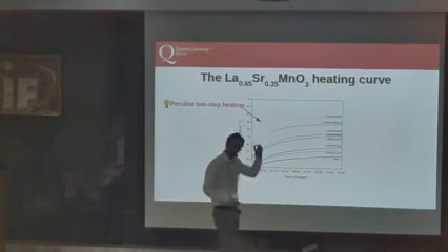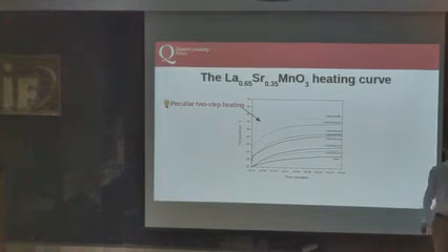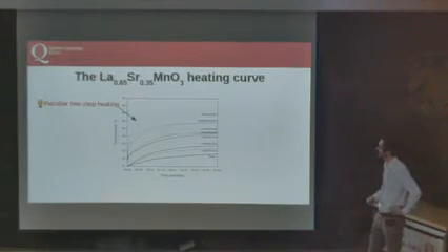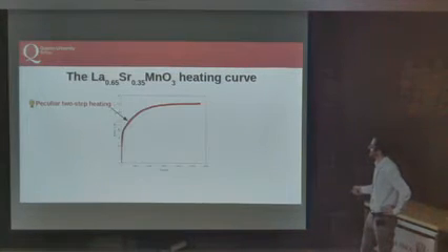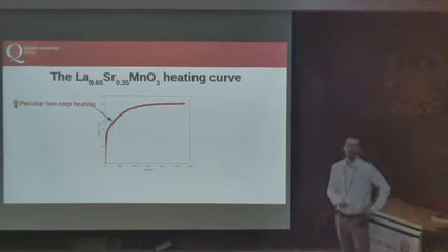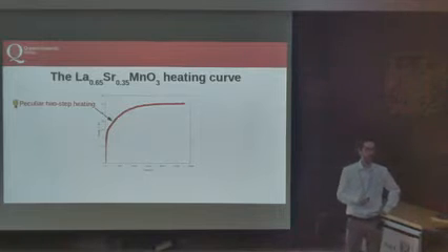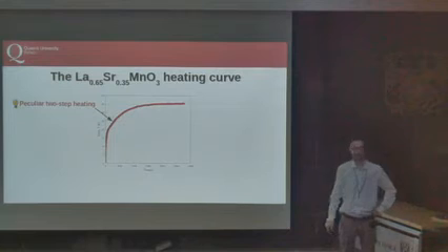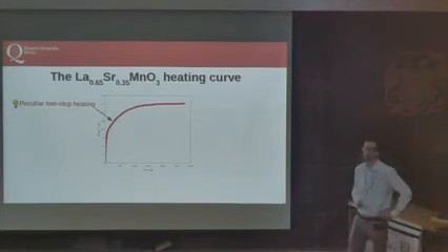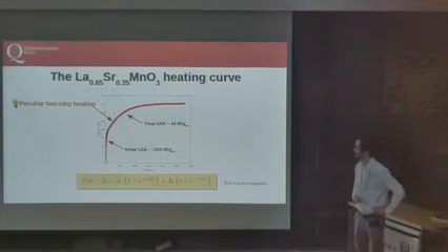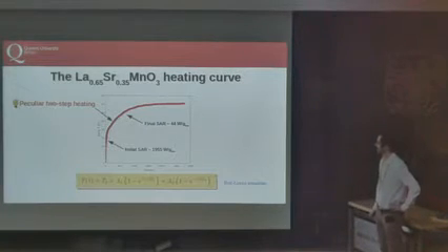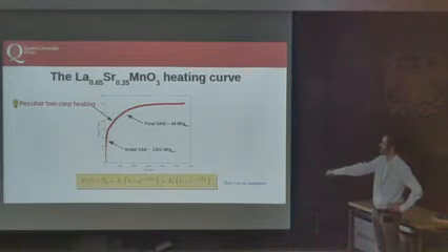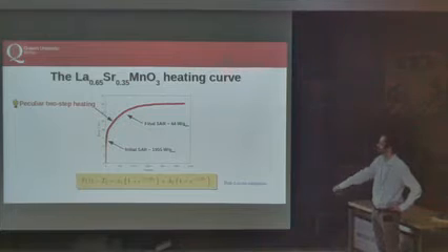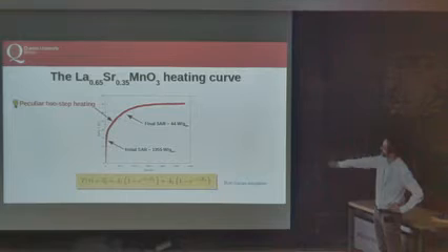Thanks. So what I was saying, this shape, 1 minus an exponential, can be understood through Newton's law of heating, so textbook physics if you want. In fact, we tried this analysis, we tried to fit everything with a single set of coefficients, and that was not possible. And it was not possible because there is this quick heating, rising up of the temperature, and then something more gentle. So of course, if you're not able to fit with one set of parameters, you do it with 2 sets. This in the literature for magnetic heating is called the Box-Lucas equation. So we fit this heating curve with the initial temperature, then some set of parameters, the first one, A1 and B1, and then the second one, A2 and B2. A1 and B1 for the first bit, and then A2 and B2 for the second bit.